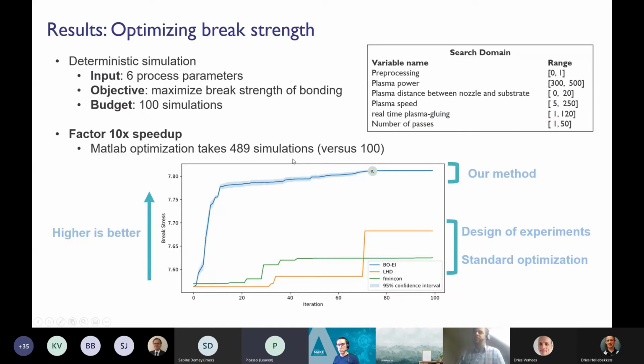So we have implemented this method in the AI toolbox, the web-based toolbox. And we validated it first on deterministic simulations. So instead of using experiments, we used a simulation instead. We want to optimize 6 process parameters with respect to the break stress, break strength of the bonding. But we only have 100 simulations to do this. At the bottom plot, we can see the evolution of the break stress for the current optimum over the number of iterations, or over the number of simulations we have done so far. We can see that our method quickly increases, so higher is better. So we really find a good optimum only after 80 simulations, or about 100 in total.